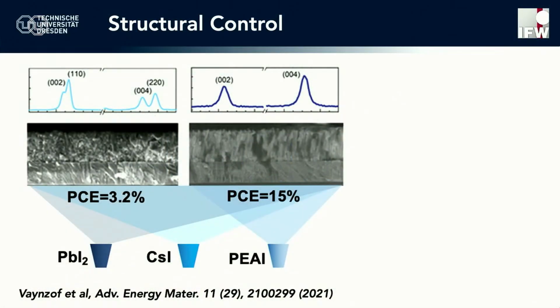Now, we worked on an inorganic perovskite. This is cesium lead triiodide. And when you just evaporate that on its own, you can see on your left-hand side, the microstructure doesn't look good. There's lots of grains, lots of defects. It's really not great. And the orientations of the grains are all different, as you can see in the X-ray diffractogram on top. The efficiency of such devices was really disappointing, only about 3%.